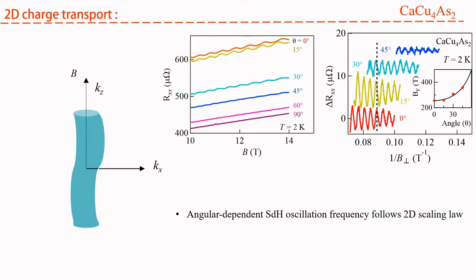High magnetic field resistivity data shows Shubnikov-de Haas quantum oscillation, and the oscillation frequency corresponds to extremal area of the Fermi pocket perpendicular to the magnetic field. As the Fermi surface is open, tilting the magnetic field changes the extremal area, and after a certain angle the oscillation frequency vanishes. Here in our case, the oscillation vanishes above 45 degrees and the frequency follows 2D scaling law, which confirms 2D parallel conduction channels present in the system.